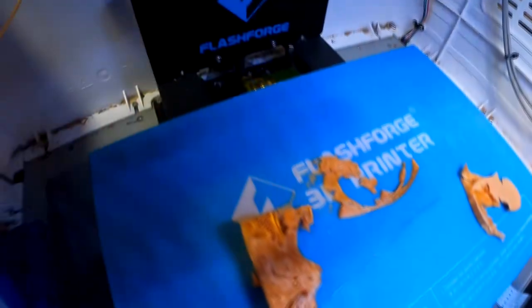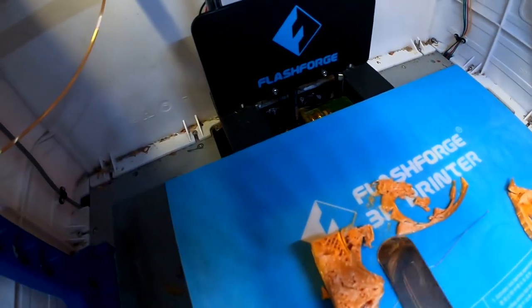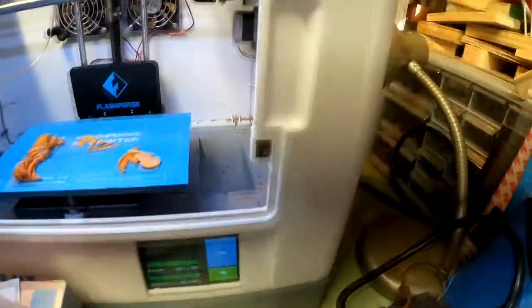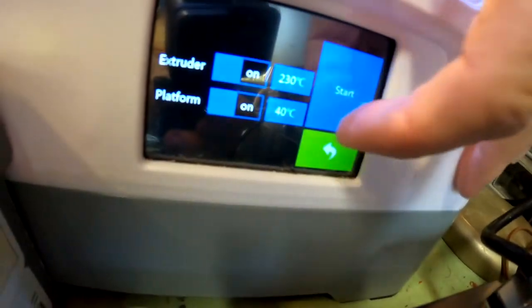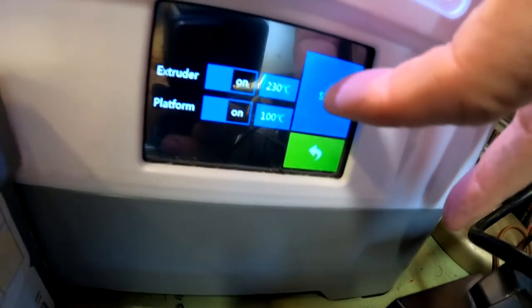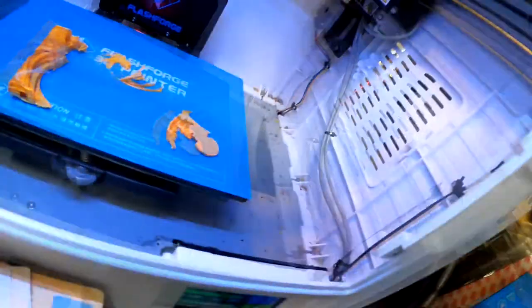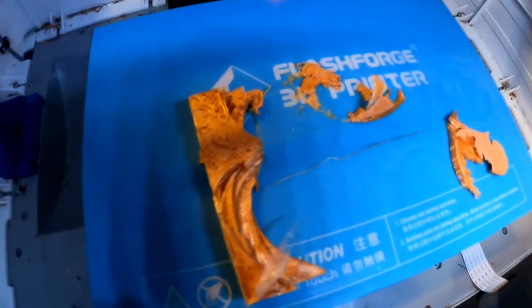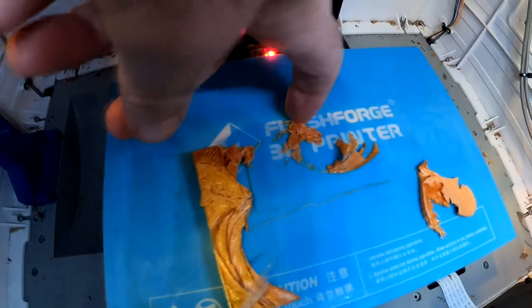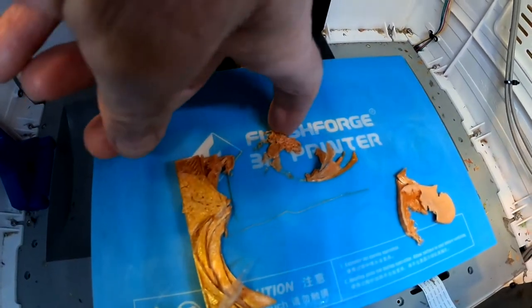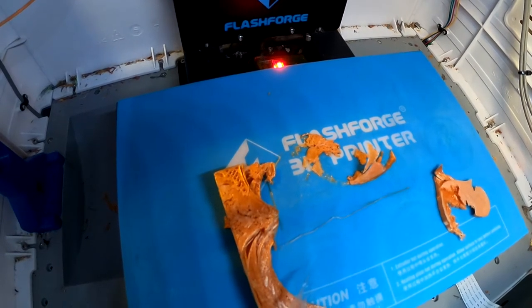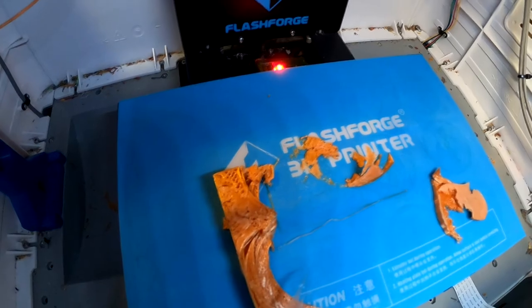I'm going to do my little hint here. To get this filament off when printing PLA and you get this really bad adhesion, it's hard to get this off. The trick is to crank the bed temperature up to about 100. 80 or 90 can work, but 100 works better. You crank it up to about 100 and then the PLA will melt at 60. At that point, this becomes very like chewing gum. You can just kind of peel it off. So that's my hint. I'll wait until it heats up and I'll show you how easily it comes off when you heat it up to about 100 degrees C.